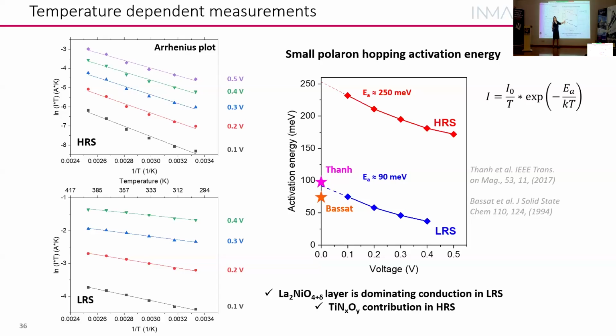And we can compare with the literature for lanthanum nickelate. That is our material, switching material in principle. And we see it has a very similar activation energy. So we really believe that for the low resistance states, the lanthanum nickelate is dominating the conductivity measurements, while for the high resistance states, where you have a much higher activation energy, there's a very strong contribution of this titanium oxynitride interlayer.